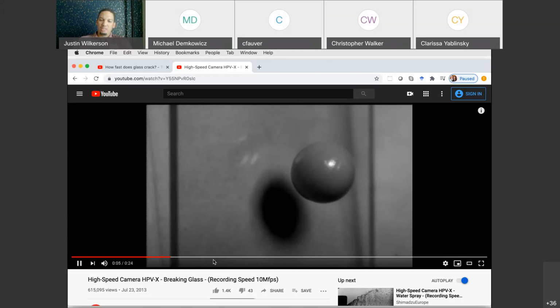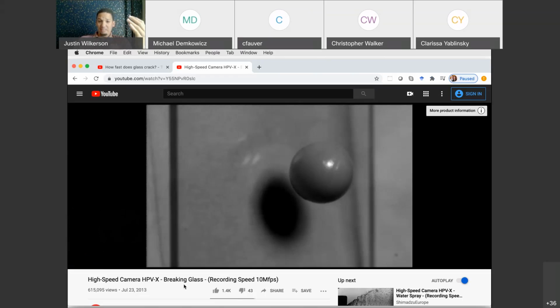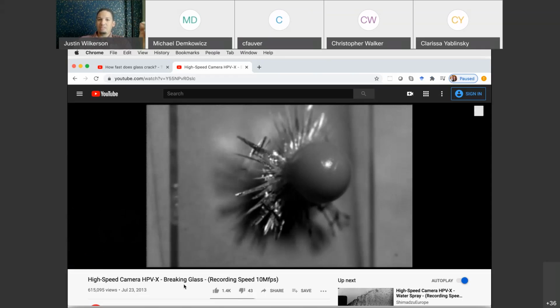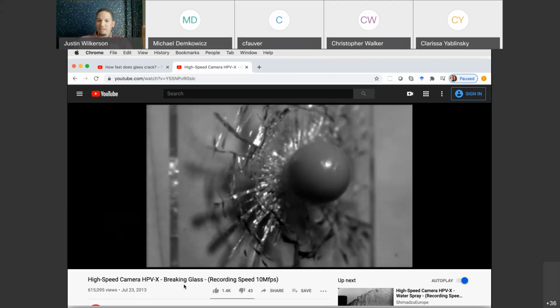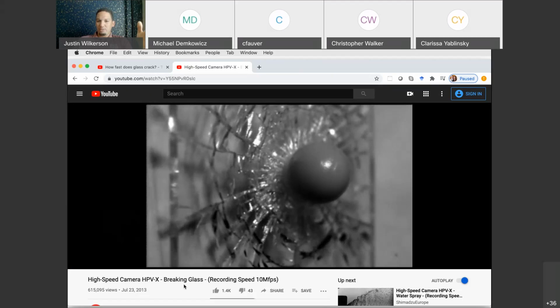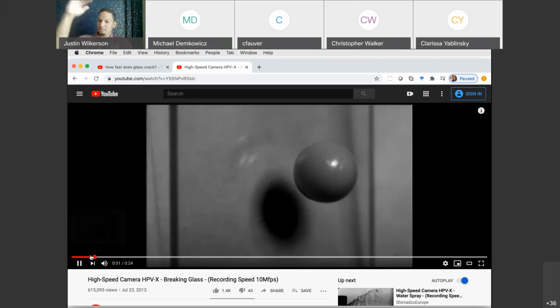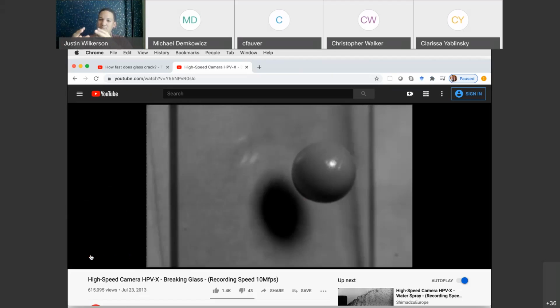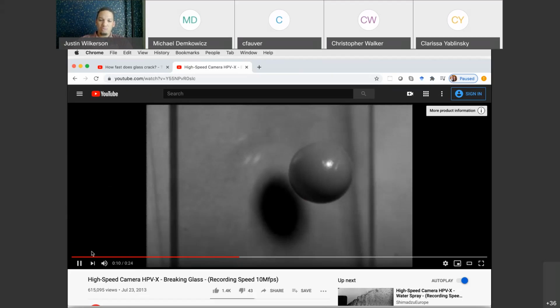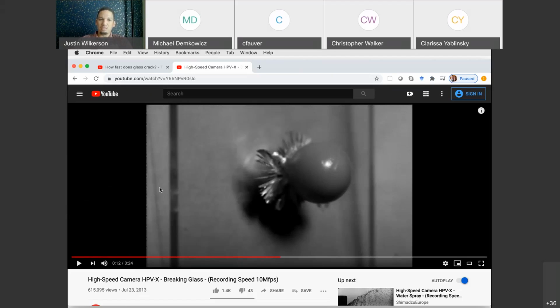But the main thing I want you to take away from this is that they move at finite speeds. They're moving at very fast speeds, but they're finite. And because of that, that means that there's a finite rate at which the material can relax stresses. Okay, so that's actually why we get to such high tensile stresses in the Spall experiment, is because the damage just can't grow fast enough to relax the stresses. Okay, and as we talk about these things, we'll find that there are many upper limits on how fast different kinds of defects can grow.